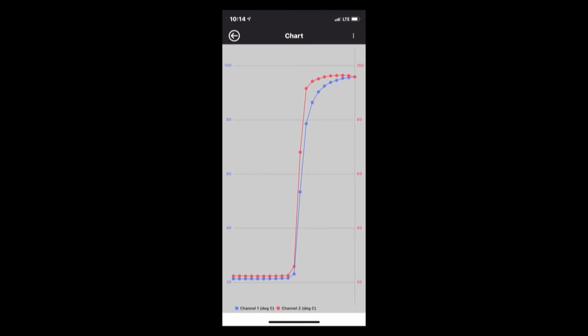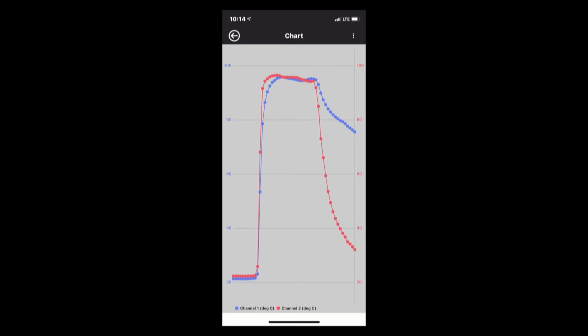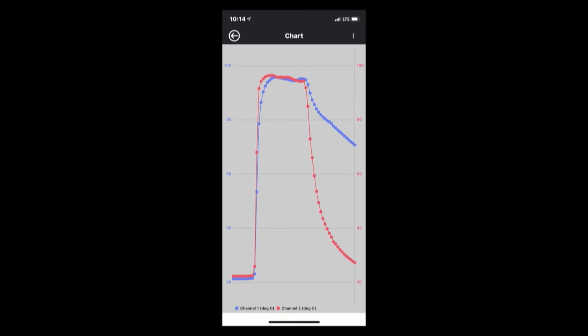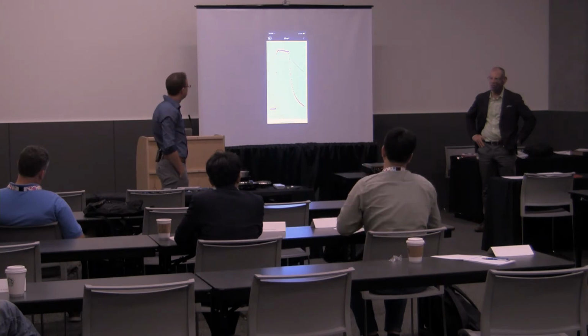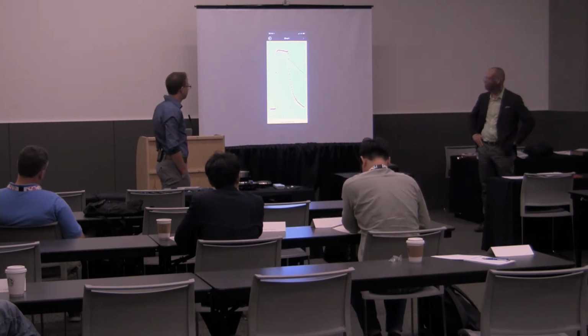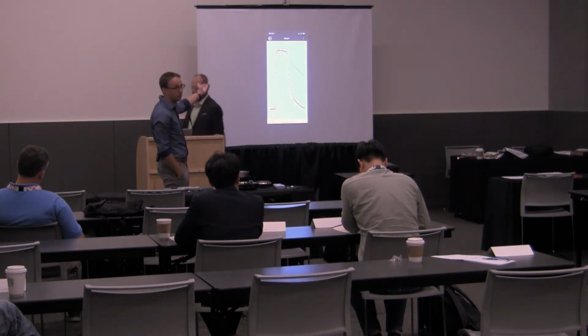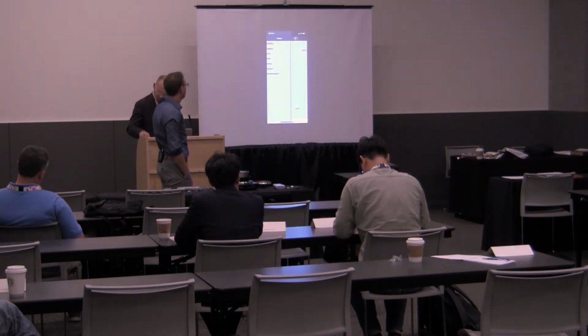It's basically sampling once a second, but you'll see just the wire probe, how much faster the response is with the lower mass. Okay. And now I'm going to remove them from the element. And as you can see, our wire probe, which is channel 2, is going back to room temperature much quicker than the channel 1 probe. I think the important learning there is that when you're using temperature probes, there's time that you have to actually wait till they normalize and get to the right point. And notice how much quicker it was to get to a high temperature and how much longer it's taking to settle back down to a low temperature.